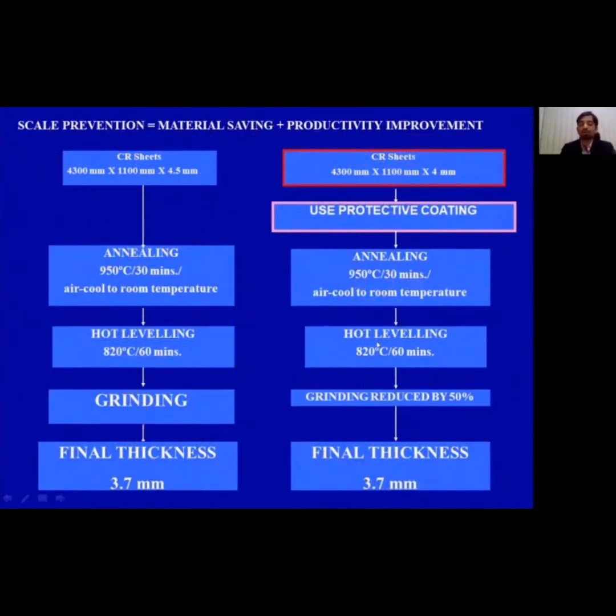This is a case of hot rolling of expensive metal alloy of high hardness. And due to consistent reduction in scaling, the initial thickness could be reduced by approximately 11%. You can see a 4.5 mm thick sheet here at the start, final thickness 3.7 mm. And by the use of the protective coating, which consistently reduced the scaling, the initial thickness could actually be reduced to 4 mm. And more importantly, the grinding time was reduced by more than 50%. Again, since this is an expensive alloy, there's an approximately 11% saving in metal itself.